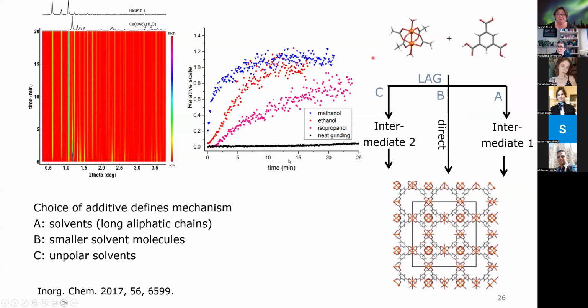And you can see here, if you don't use any solvents, it takes a bit. So the reaction goes at some point to completeness, but if you use methanol, for instance, that's a really fast reaction. Within 2-3 minutes, you have your final product. We investigated that a bit closer and found out that it strongly depends on the solvent which way the reaction takes. So we have a direct reaction with smaller solvent molecules. If we use longer solvents, then we see an intermediate formation. And if we use unpolar solvents, there is yet another intermediate.